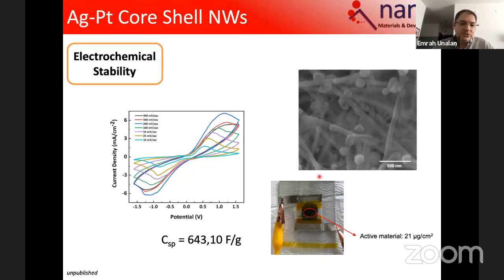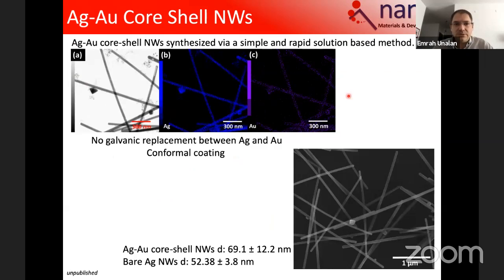And the next thing was to push this thing. So 0.5 volts was our limit. So can we push this to higher potential? So 1 volt or 1.5 volts. These devices do survive. So we try different materials. So this is polyaniline. So as you see these drops, and I believe there is some sheet-like coating also onto silver platinum nanowire thin films. So it is increasing the stability window. So the electrochemical stability is also increasing with the platinum deposition.